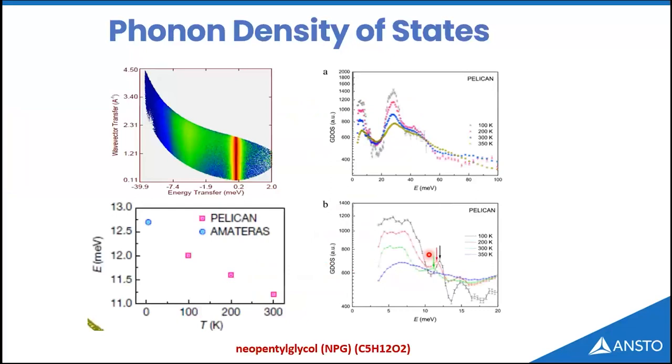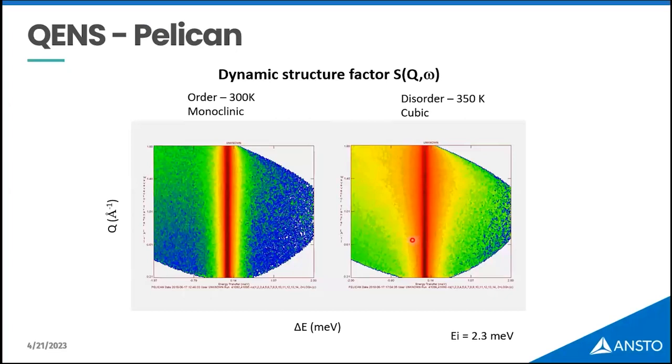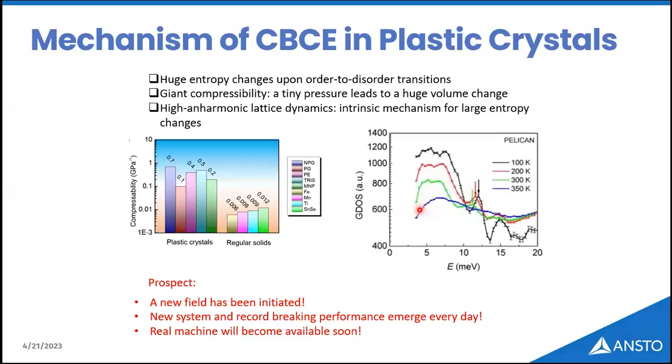As a typical example of the plastic crystals, we chose NPG. You can see this is the phonon density of states measured on Pelican and AMATERAS at J-PARC. Especially, we identified a peak around 12 meV that has strong temperature dependence. If a solid can be described by harmonic oscillation, there should be no temperature effect in the phonon density of states. So this strong temperature effect gives us direct evidence of the strong anharmonic lattice dynamics of these materials. And this is the QENS from Pelican, showing the order to disorder transition upon phase transition. So from combining all the other studies with inelastic neutron scattering,